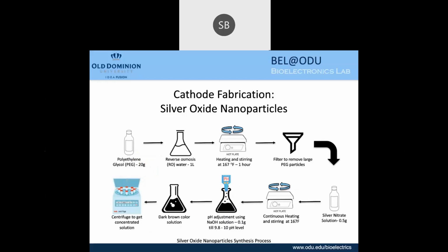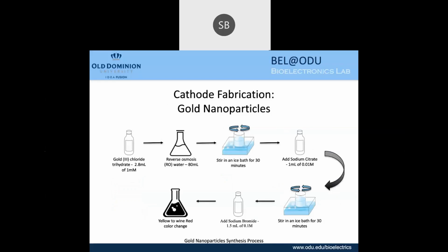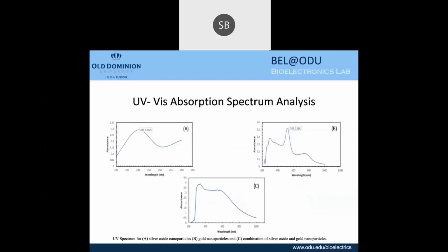For silver oxide nanoparticles, we used PEG, polyethylene glycol, with continuous heating and stirring to remove the PEG. We used a filter, added silver nitrate, and then adjusted the pH using sodium hydroxide, and we got a resultant silver oxide nanoparticle solution in a dark brown color. For the gold nanoparticles, we started with gold chloride trihydrate, then added sodium citrate and sodium bromide, and saw a yellow to wine red color change.